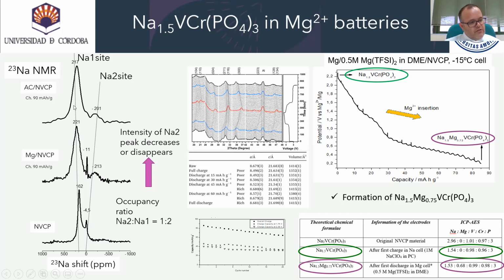Only small changes in sodium 1 peak intensity are observed, consistent with the relatively small lattice parameter changes seen in XRD. These results are reasonable because the sodium extraction is coincident with vanadium oxidation, which is expected to result in an overall shift of the 23 sodium resonance. Also, the small change in sodium 1 peak intensity is consistent with the relatively small lattice parameter change seen in XRD.